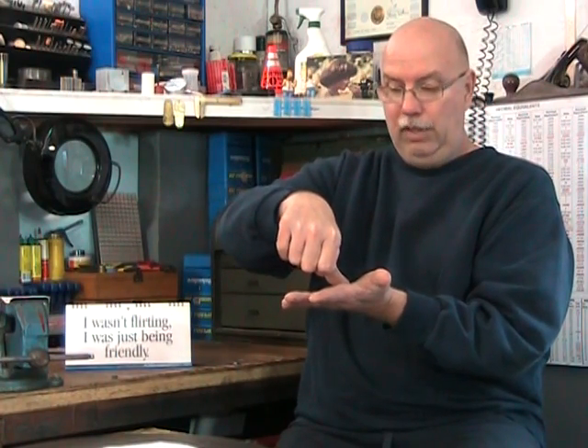Now, the Brinell test uses the standard one, a 10 millimeter steel ball. It's going to be placed on the surface of the part to be measured as far as hardness goes. Then we're going to apply to the ball a 3,000 kilogram force. Now obviously that ball is going to penetrate the surface of the piece of aluminum, and it's going to create a footprint. If I calculate the surface of that footprint in square millimeters and divide the load applied by it, in this case 3,000 kilograms, I will obtain the Brinell hardness number. The Brinell number obtained, the HB number, is proportional to the hardness of the material.